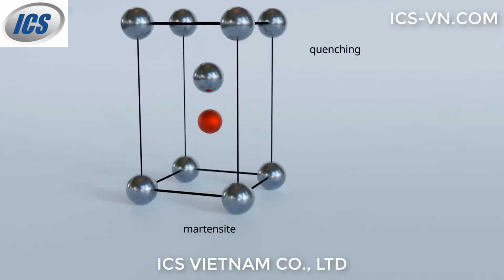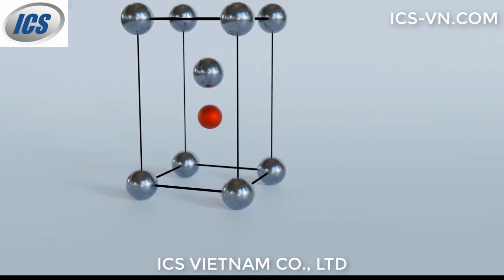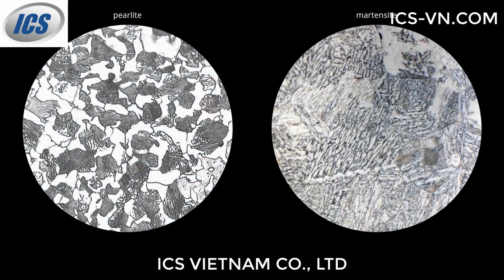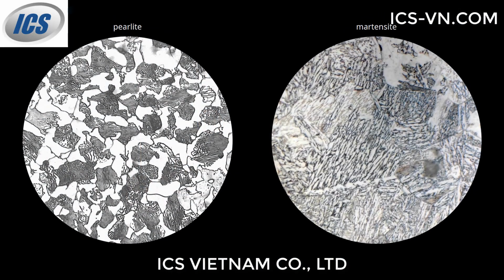If the cooling rate is too low, not enough martensite is formed. The carbon atoms can still partially diffuse and form cementite. An intermediate microstructure is formed which, in terms of its properties, lies between the perlite microstructure and the martensite microstructure.